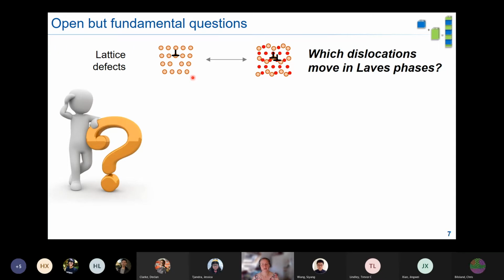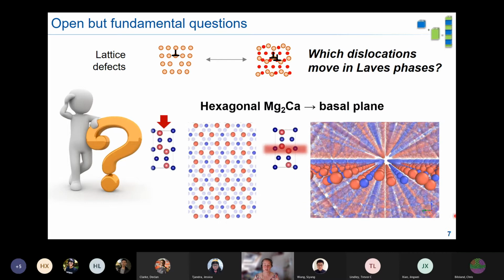So in undergraduate teaching, we draw edge dislocations, right? We draw them into a primitive cubic lattice most of the time. We also think about FCC and BCC crystals. But if we look, for example, in Laves phases, that's the crystal that's shown here in one projection, they're the most common intermetallic packing, a common phase, but we don't even know how to draw a dislocation in there. It's very difficult to even think about how to draw an extra half plane into this. So that's where we started out.